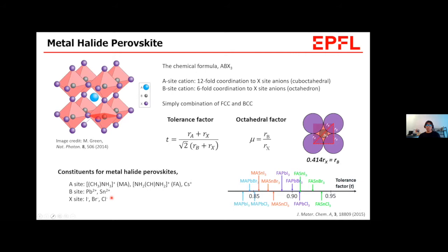And regarding the octahedral factor, with the radius of these B-site cations, lead and tin, they have around 120 picometer radius. The octahedral factors are all calculated to be more than 0.5, which is larger than this, so they meet this octahedral factor condition as well. So we can get these stable perovskite materials.